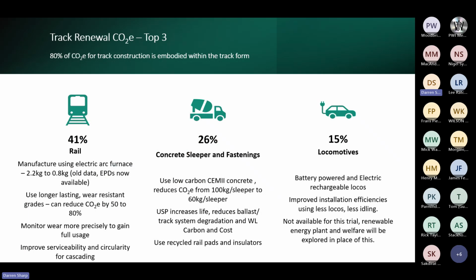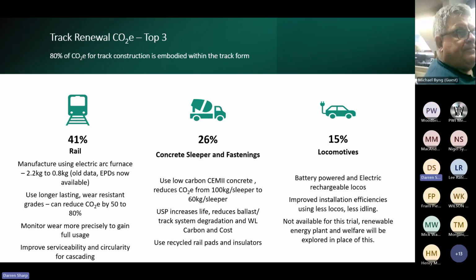In terms of rail, we've been looking at how we can reduce the carbon in our current rail by using electric arc furnace rail. So that can reduce from 2.2 kilograms per kilo, so it's quite a high figure for rail, down to 0.8. So that's quite a large reduction if we start to use green steel, which is electric arc furnace steel, and it uses recycled steel as well, at a higher percentage. We could use longer lasting rail, wear resistant grades as well, so that could last longer. So we can look at a life cycle reduction of carbon. We could monitor wear more precisely using laser profiling and rail profiling data more accurately, rather than using older methodologies, and improve the serviceability and circularity for cascading. So there are other things we can do to improve that.